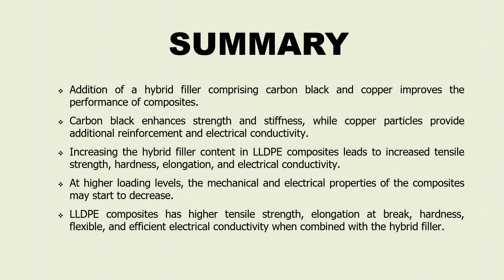In summary, addition of hybrid filler comprising carbon black and copper improved the performance of the composites. The carbon black enhanced the strength and stiffness, while copper particles provide additional reinforcement and electrical conductivity. Increasing the hybrid filler content in LLDPE composite leads to increased tensile strength, hardness, elongation, and also electrical conductivity. Nevertheless, we might find at higher loading levels of fillers, the mechanical and electrical properties of the composite may start to decrease.